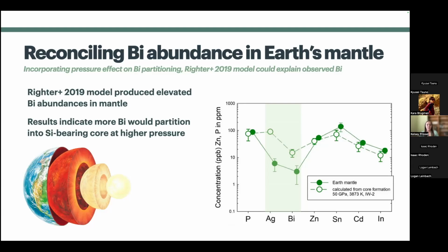If we were to model core formation and incorporate that change, we would be able to put more bismuth into the core, and that would result in a lower calculated concentration of bismuth in the mantle. If you look at this previous mismatch for bismuth, if we were able to incorporate that effect of pressure, we might be able to reconcile the gap between the observation and the model. This is an exciting implication of the findings that we presented today, and I'm going to be presenting on this in more depth, specifically the bismuth problem, or solution rather, at AGU in December.